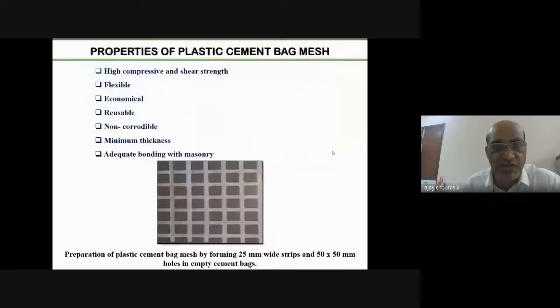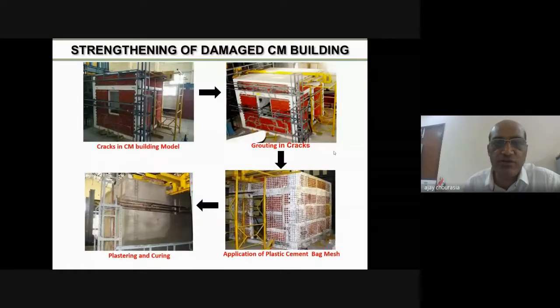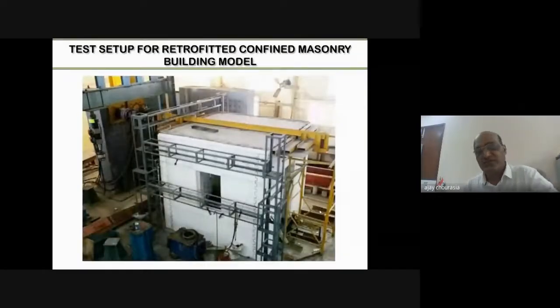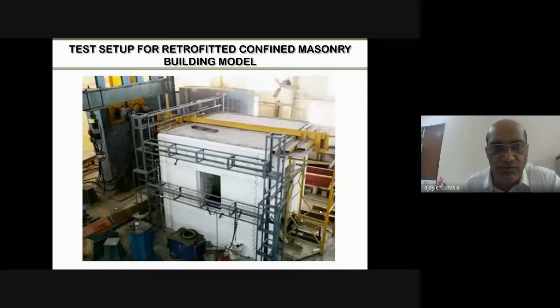After selecting this particular approach, a damaged confined masonry model was first of all grouted using cement grout, and after grouting, the entire building was jacketed using the plastic cement bag mesh, as I have discussed just now. It was provided on either face of the walls, and then embedded within the plaster of 15 mm thick 1:4 cement sand mortar. And again, the fully retrofitted building system was ready for the lateral load test.